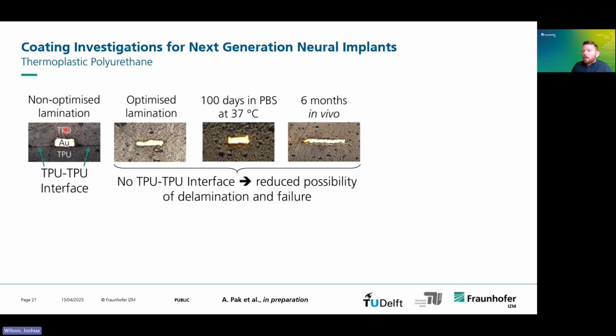And when you build up these multi-layer structures, what you see is you have a lot of interfaces here. So there's a TPU interface, there's a TPU gold interface, and all of these interfaces are potential points of failure. So anywhere where the water can get in and travel towards the electronics to start corrosion, or even just delaminate the two different polymer films to separate them, this is going to destroy your device. So the major advantage of using polyurethane, when we laminate it in an optimized condition, a high enough temperature that this thermoplastic can melt, is that when these layers are melted together, you remove this interface. And thereby you reduce the possibility of delamination and failure. And this material stack is stable in vivo for 6 months, almost certainly for much longer.